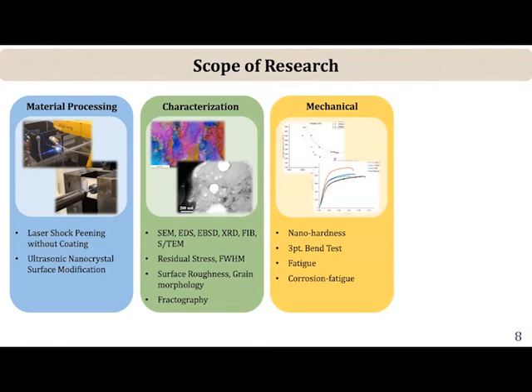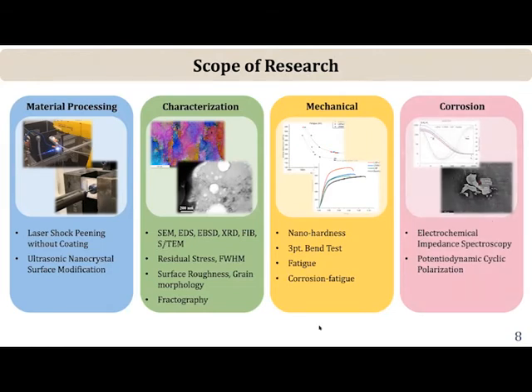The mechanical property tests, using hardness, nano indentation tests, principally 3-point bend tests, as well as fatigue and corrosion fatigue tests. And because when you're dealing with surface treated materials, 3-point bend or 4-point bend tests are generally more suitable because you're able to orient the sample in such a way that you can really test the effect of the mechanical surface treatments. And then corrosion behavior is principally studied using electrochemical impedance spectroscopy, as well as potentiodynamic cyclic polarization.